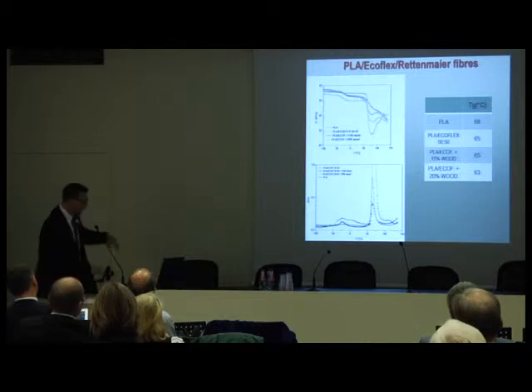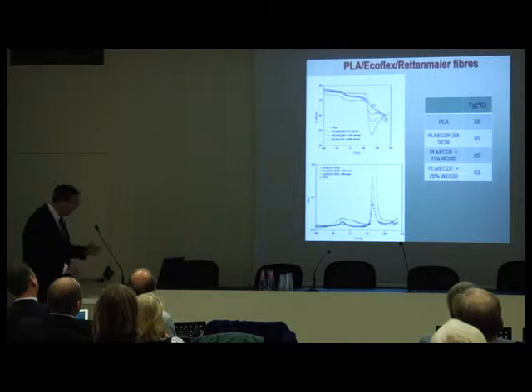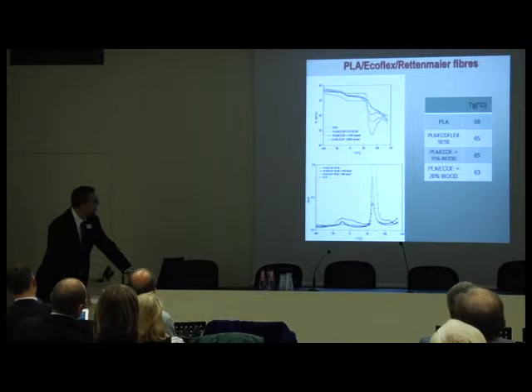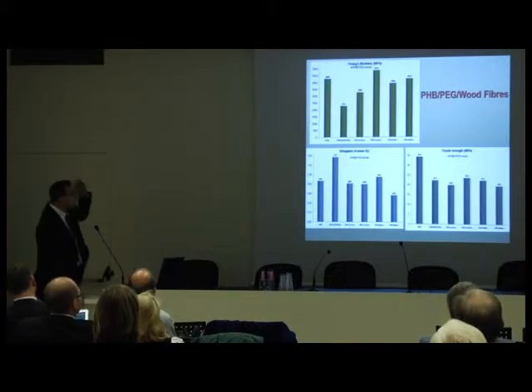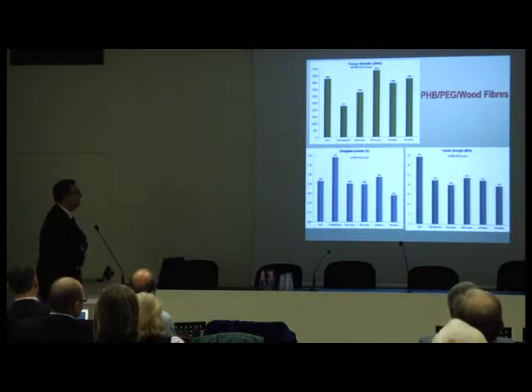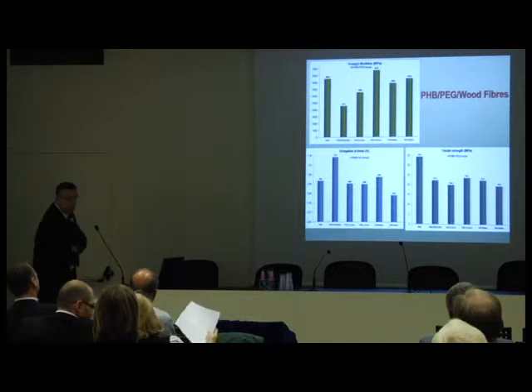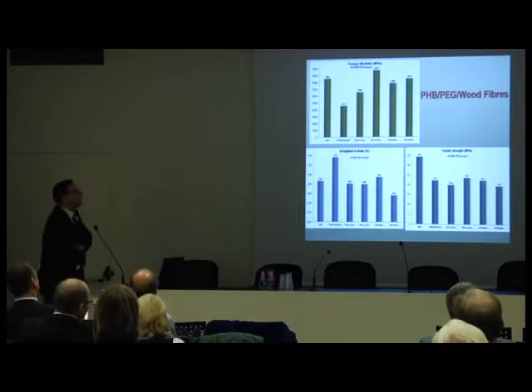But with fibers, you see here that with 20% fibers, the drop in modulus is very low. So this is, I think, an interesting result that we got from this work. And we also did some work on PHB and PEG, and we obtained some PHB from Biomer, which is a company in the Industrial Advisory Board. And they have their own formulation, which is very good, in fact. But we tried pure PHB and tried to modify it with PEG.